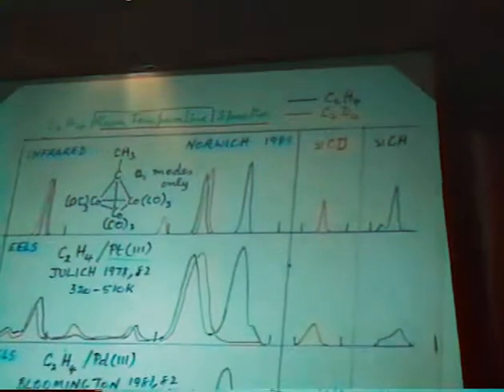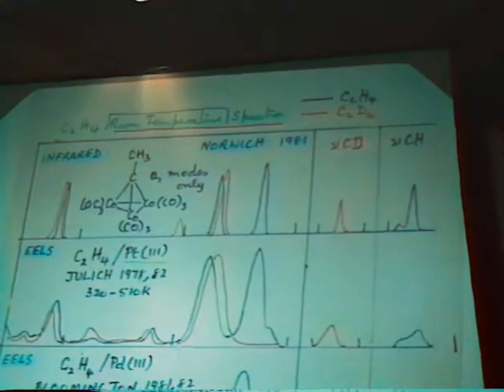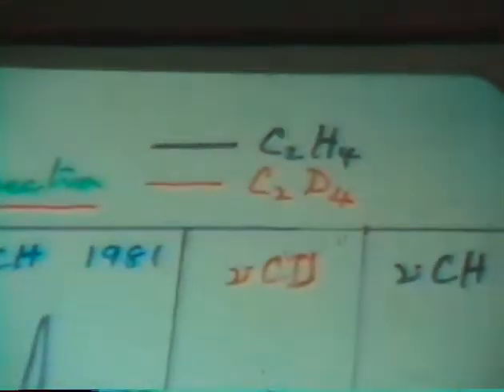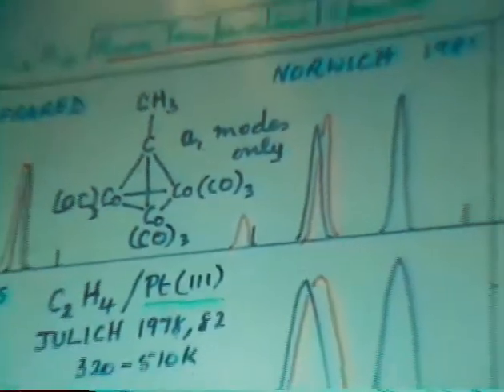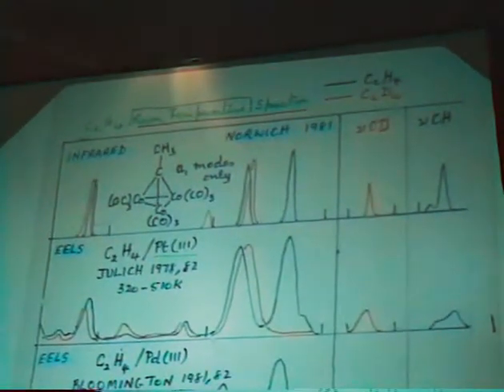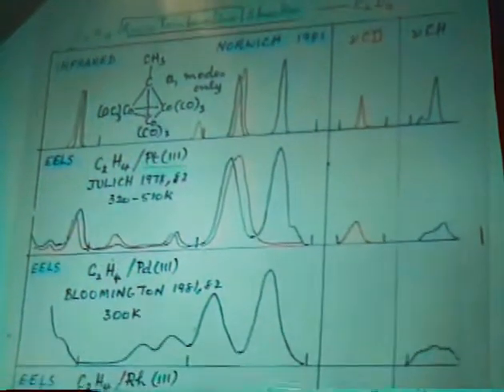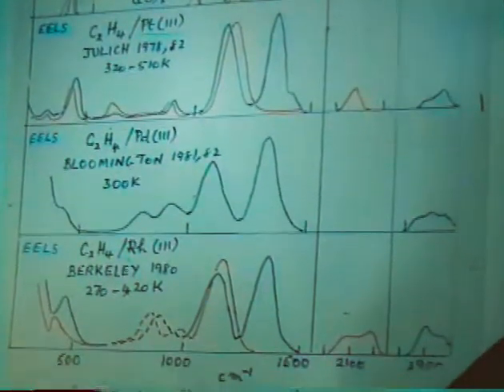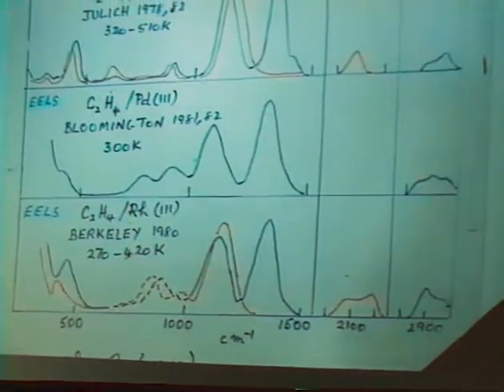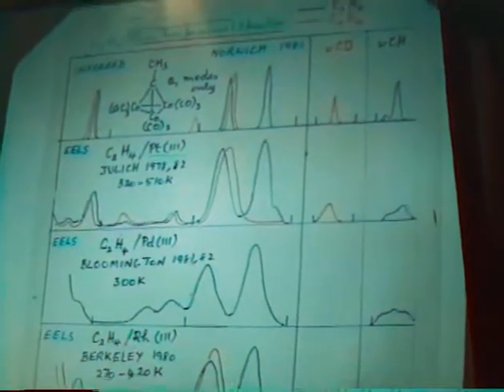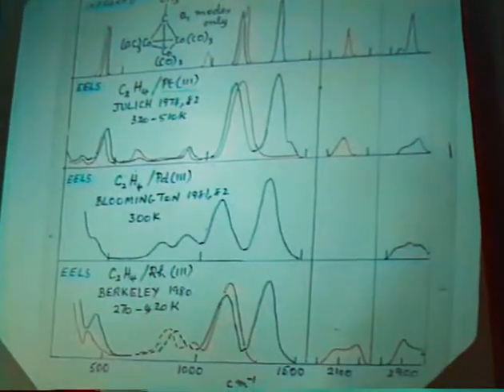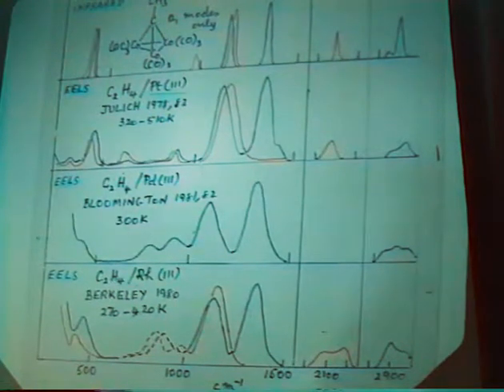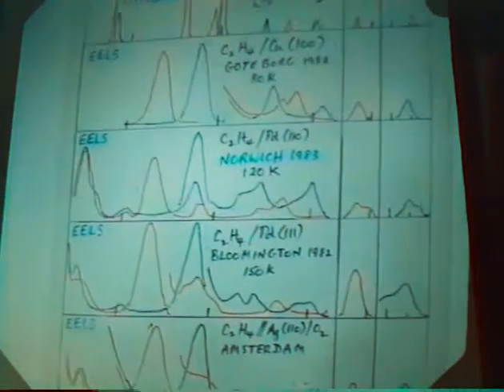Well, here are some of the spectra on different metal surfaces, which obviously are from the same type of species. And what I have done is to put at the top the infrared absorption bands from the model compound, but only drawing out the perpendicular modes which we expect to see on specular on the surface. And you can see pattern recognition, while the black ones are from the C2H4 absorption and the red ones from the C2D4 absorption. There's no doubt that that is indeed the species on those particular surfaces. And you'll notice they're all 111 surfaces with threefold sites, which is what you have to have for an ethylidyne species. Well, that was at room temperature, and Ibach had also done work at low temperature with ethylene and got a different spectrum. So you could apply the same technique to other species for which you had metal cluster compounds.